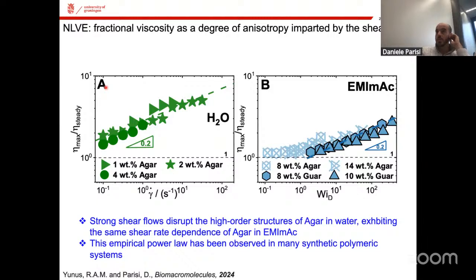For instance, this is how the degree of anisotropy depends on the deformation rate. And this is basically something similar to what we obtain for water and for ionic liquids. So until you reach a certain degree of stretching of the chains, nothing happens. But when all the polymer chains are stretched, this anisotropy increases with the power of 0.2. And this has been seen also with many synthetic polymers as well.